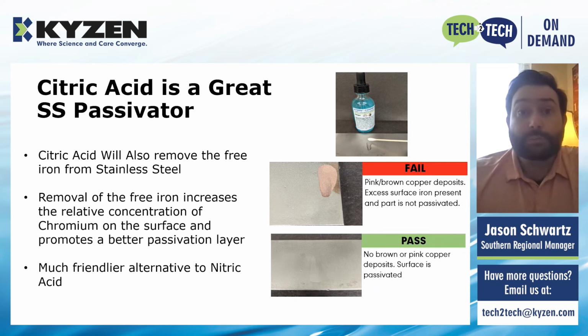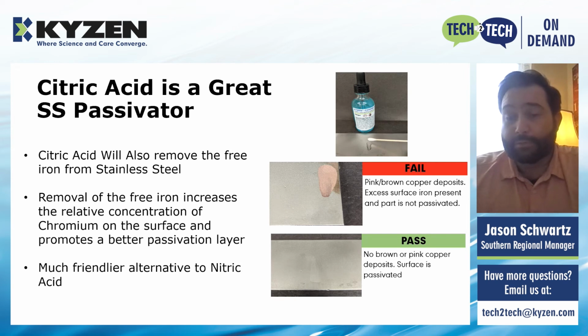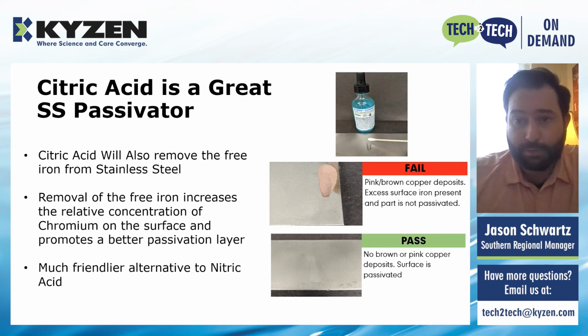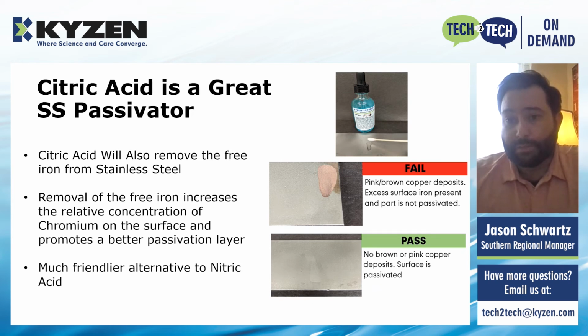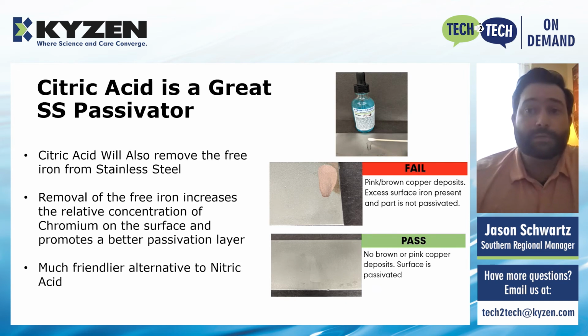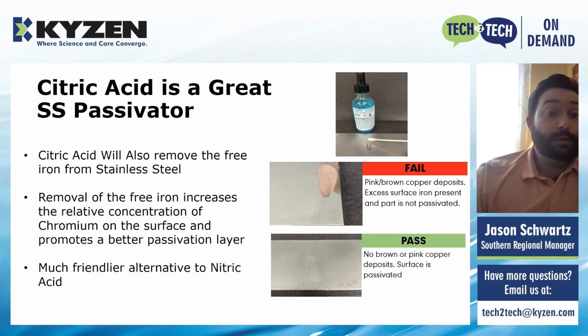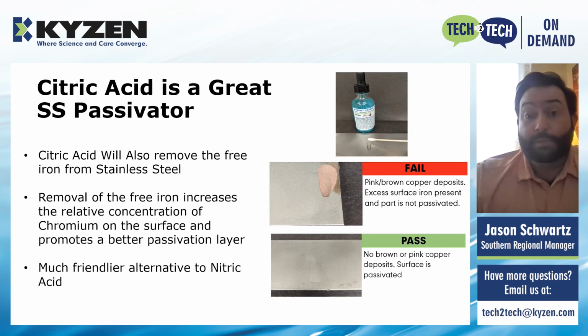And that's where something like the copper sulfate test, which you can see on the right, comes in, where you dip a little bit of copper sulfate solution onto a stainless steel part. If there's free iron left on the surface of that part, it's going to show up like that top picture where it says fail. That pink brown copper deposits are going to bind to the surface iron and show you a fail. Whereas once you've passivated something with stainless steel, you've removed that free iron and you're going to pass the copper sulfate test. And again, citric acid is a much friendlier alternative to nitric acid, which has been the standard for passivation for many years.